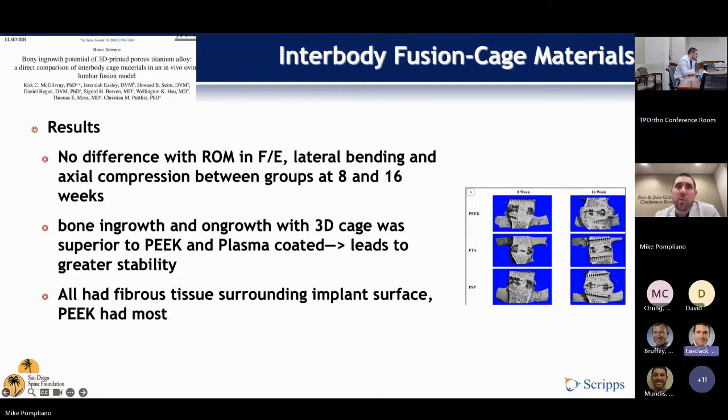No. Well, short answer: when you see those charts with the differential of modulus, with stainless steel on the top end and bone on the bottom end, those are pure material property assessments. If you change the structure of that material, you change the relative stiffness. So you can't look at materials in a simplistic modulus perspective anymore when you can modify their structure.